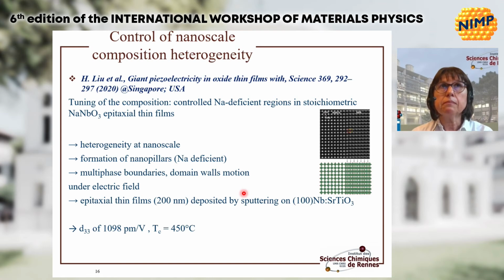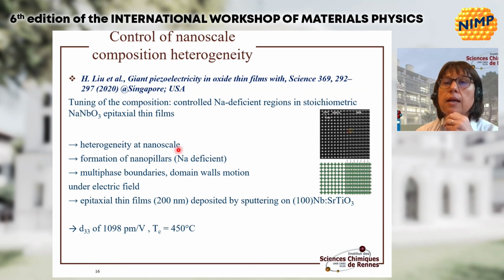More recently, by nanoscale control of the composition in sodium niobate, Liu et al. have shown that it's possible to obtain very high piezoelectric coefficients with a high Curie temperature. The nano-engineering of the composition consists of obtaining heterogeneity in composition at nanoscales. For this purpose, a slight deficiency in sodium has been introduced in sodium niobate films.